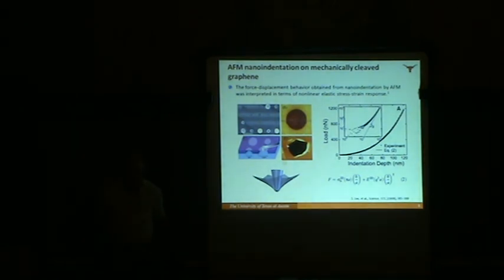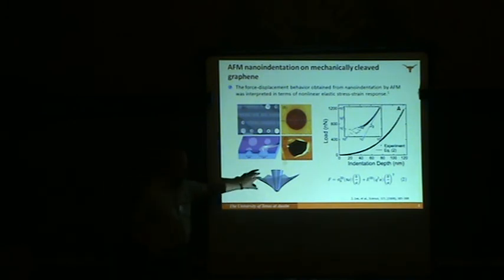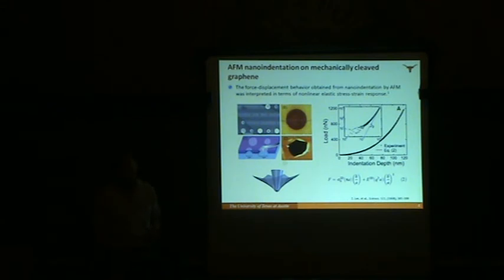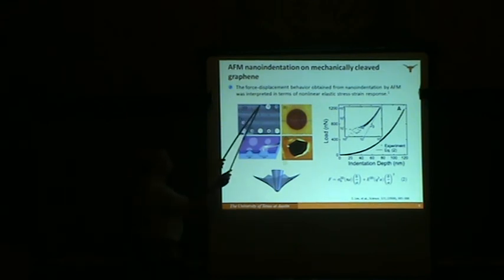So there has been very nice work from Columbia University. We were asked earlier, could nano-indentation be useful? They actually used indentation, but with an AFM diamond tip of 2 different radii of curvature. In these experiments, they're micromechanically exfoliating, using the Scotch tape method, onto an array of alternating 1.5 micron and 1 micron holes.